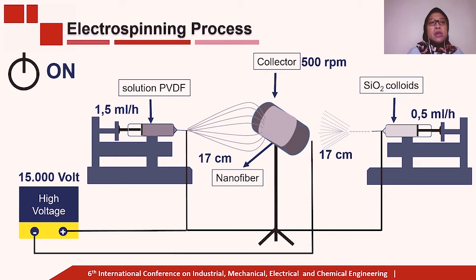This is the parameter process of the electrospinning. PVDF solution electrospinning process for 2 hours, while the SiO2 was only 1 hour. The electrospinning process was simultaneous between PVDF and SiO2 colloid. PVDF solution and SiO2 colloid syringe needle is 17 cm from the metal needle to rotating cylinder collector. The collector rotation speed was fixed at 500 rpm and the DC high voltage adjusted at 15 kV. The flow rate of PVDF solution and SiO2 adjusted at 1.5 and 0.5 ml per hour respectively.